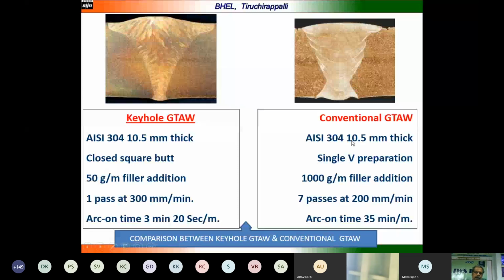50 gram filler addition is required when you are using keyhole GTAW, and we require 1000 gram of filler for conventional TIG welding. One pass at a speed of 300 mm per minute, 7 passes at a speed of 200 mm per minute has been made. Arc on time is 3 minutes 20 seconds, whereas in conventional TIG it is 35 minutes. Almost 1/10 of the time, the welding can be completed very easily with the same quality or with improved quality. And this process can be used as an autogenous process also, as well as with filler wire.